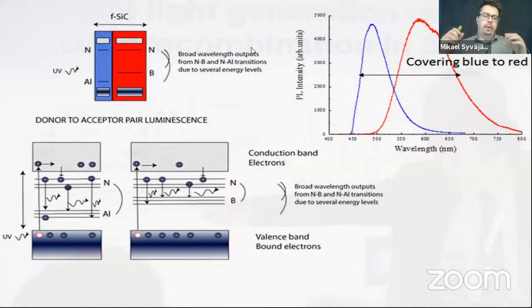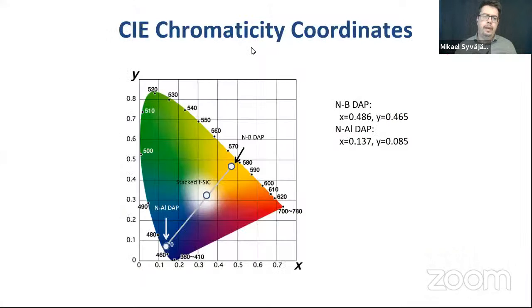The concept is that you have two layers with different dopants. In this luminescence, it comes out as a broad spectrum, and if you have two layers, you have two broad spectra. If you do this in 6H silicon carbide, it comes in the visible region. So the light is broad. There's no dominating peak like in the blue LED. If you combine these, you can get a pure white light using silicon carbide. That is the exceptional thing with this LED using this doped material.